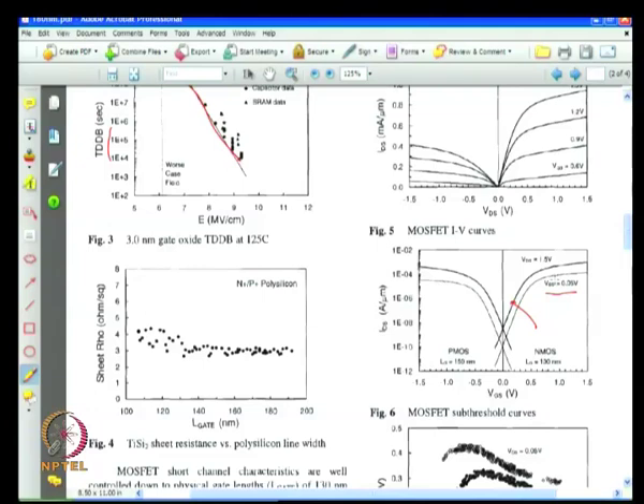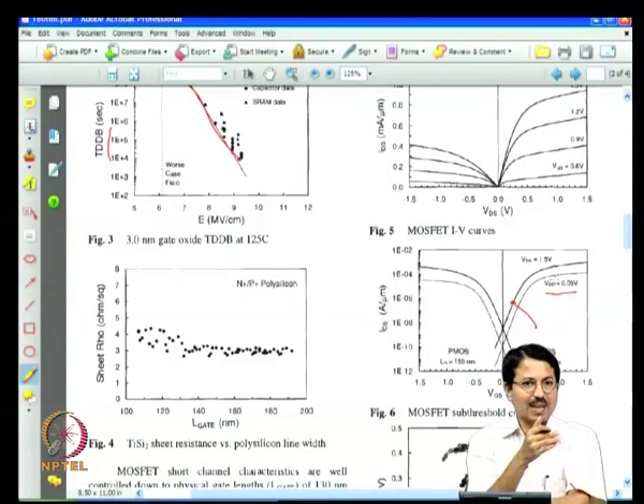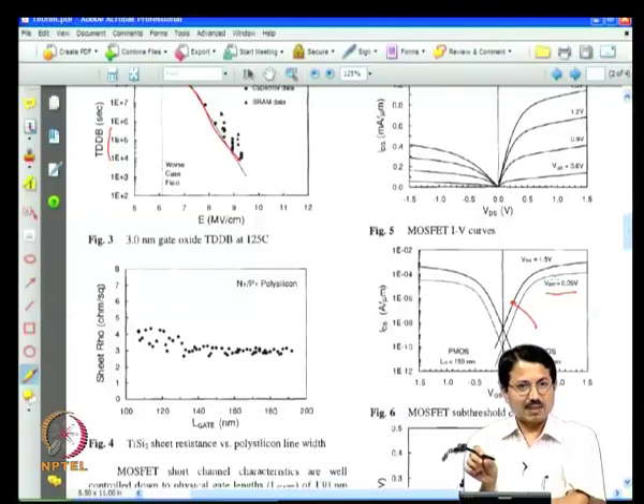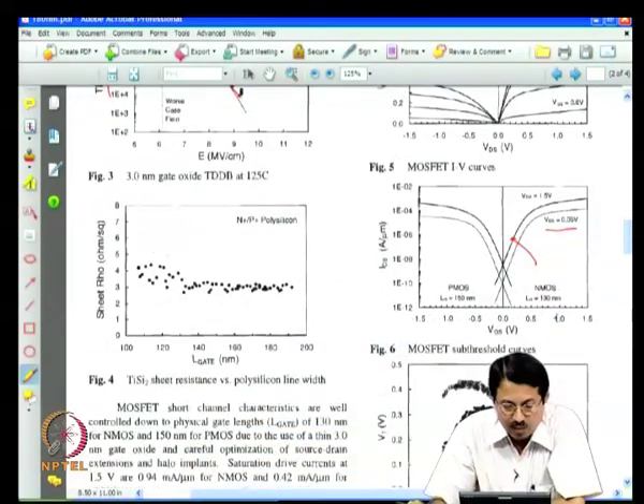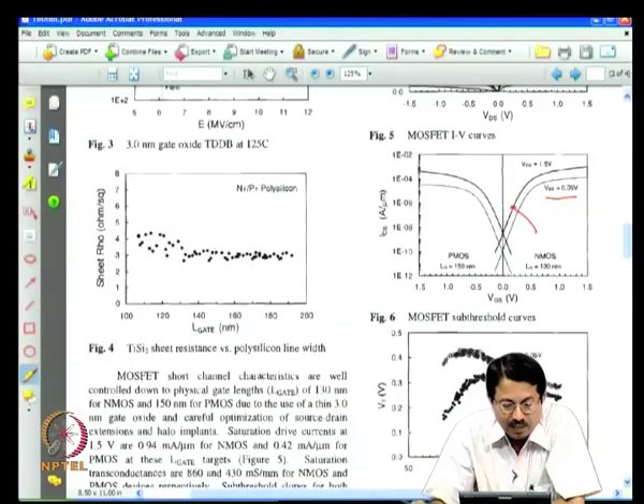If you have larger drain voltage for the same gate voltage, you get larger current because your drain electric field will influence the injection at the source side, especially in these nanometric dimension transistors. Okay. So, this is just to show that your polysilicon gate, because of the silicidation, has reasonably low resistivity. Sheet resistance is of the order of 3 to 4 ohm per square, which is fairly good.